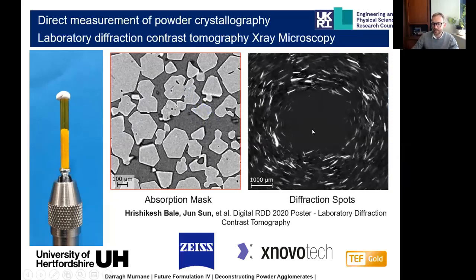But at the same time, we build up a diffraction image at a particular orientation of the powder, and we build up that diffraction image, which is the powder diffraction spots. So it's possible using the patented algorithms from Xnovotech that work with the Zeiss instruments, and I believe these are the only instruments that are capable of carrying out this analysis. We can carry out back calculation algorithms to show what the orientation of a crystal is to produce these diffraction spots. So we're able to now identify the specific crystal within this powder blend from the diffraction spots, and we're able to identify what the crystal plane orientations are from those diffraction spots.